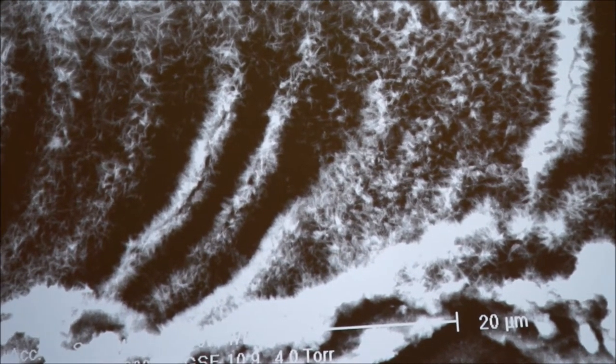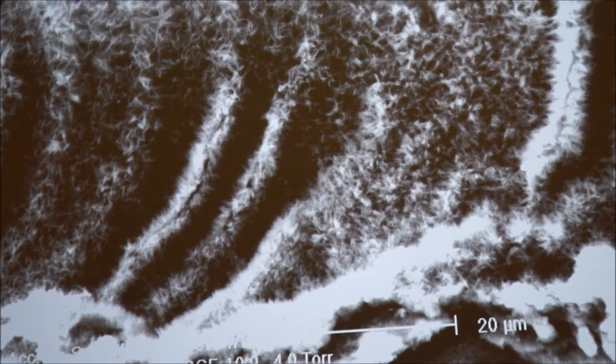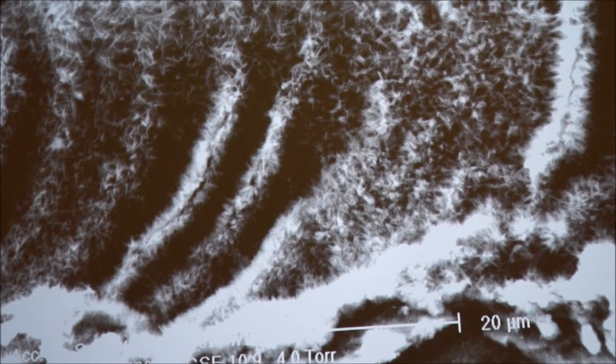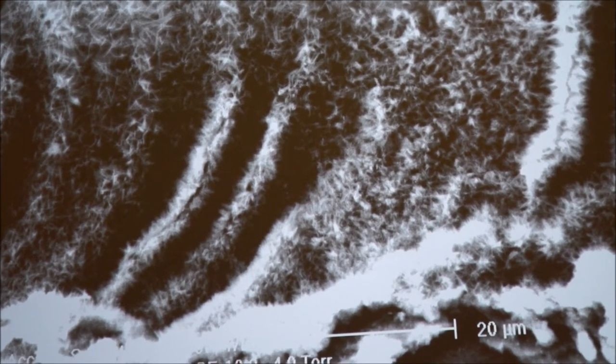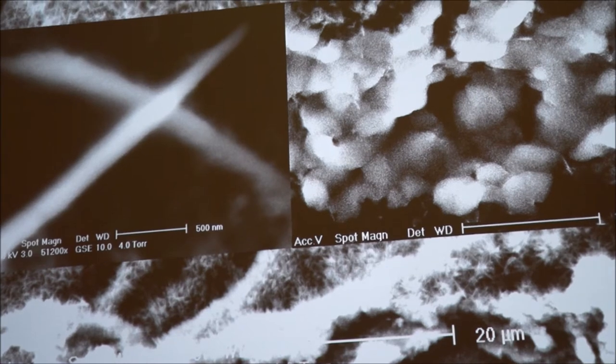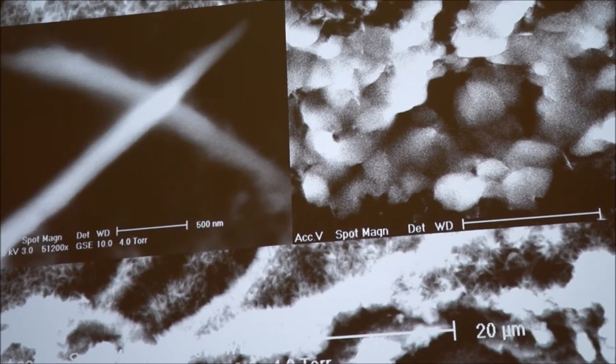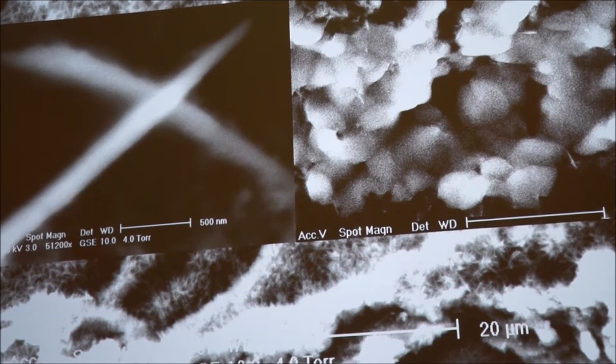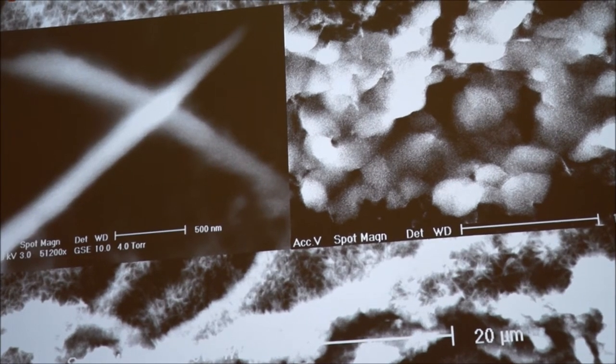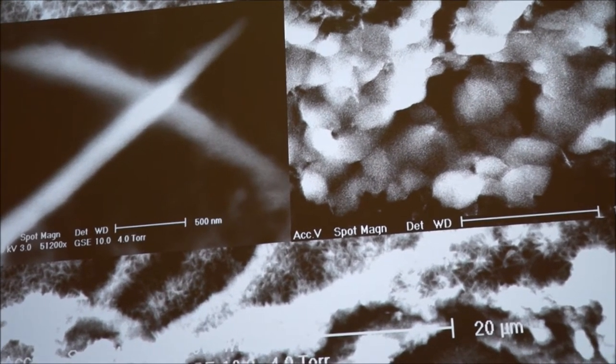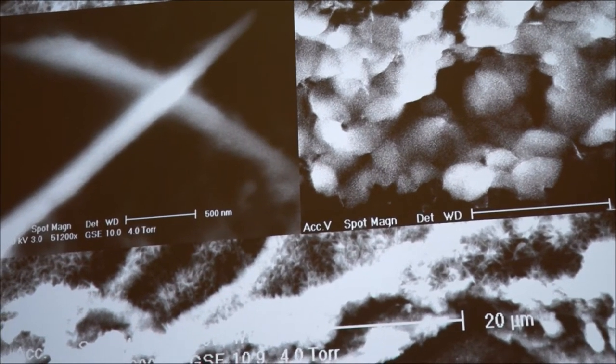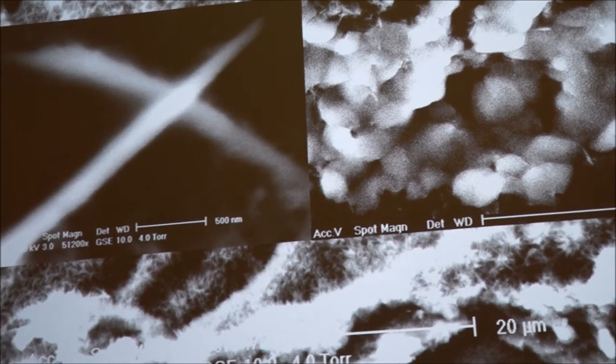If you see right on the right-hand corner, you see kind of globules, and the rest of this is just crossed spines. Here's a zoomed image of those. What might be happening here is that alanine is coordinating to minerals within the chimney and stabilizing certain crystal surfaces in order to hinder growth in some directions and cause the needle shape to form instead of whatever was forming earlier.